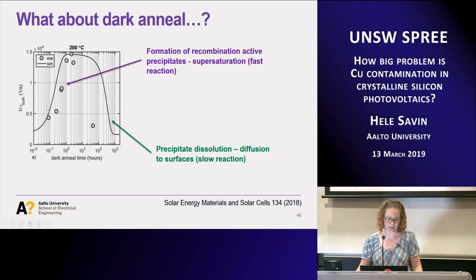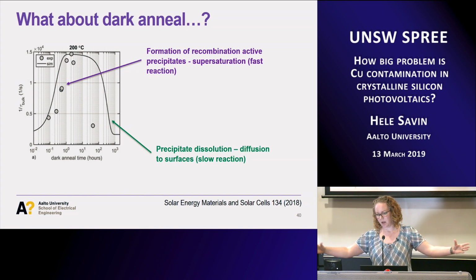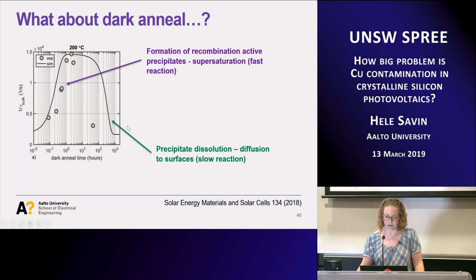And what we observe is a very familiar looking curve. So this is an inverse lifetime. First the degradation, and this is when the copper precipitates start forming. But if we have high enough temperature, let's say 200 here, we actually have a competing reaction. If the copper precipitates that are formed are really small, they start dissolving and then finally diffusing back to the surfaces or to the emitter. So this is causing this increase again in the lifetime, but the time scale is much lower.